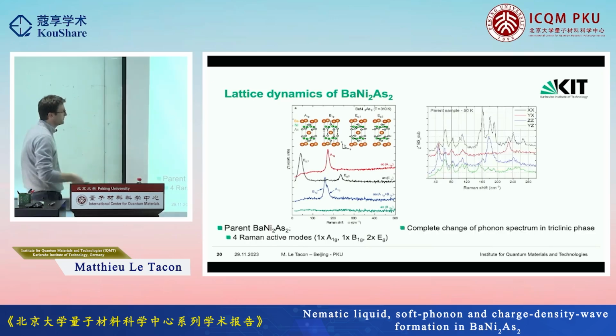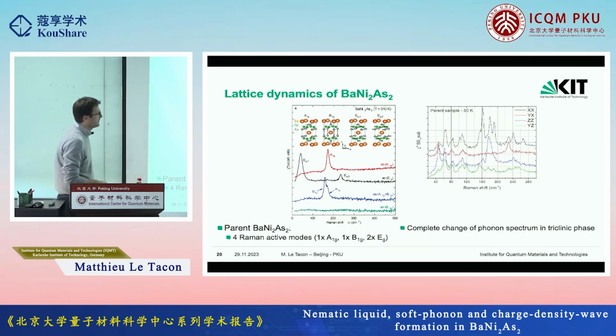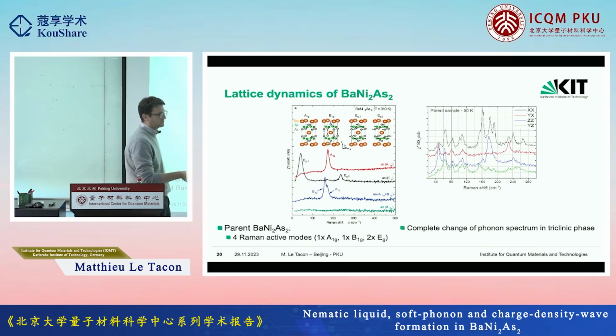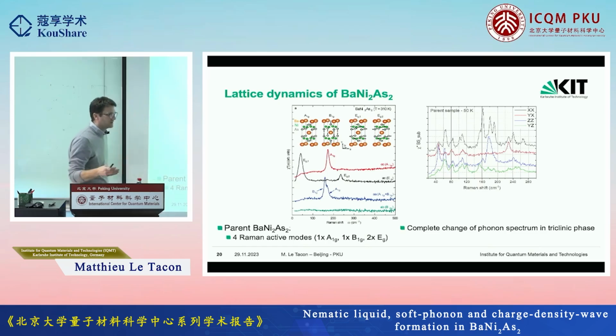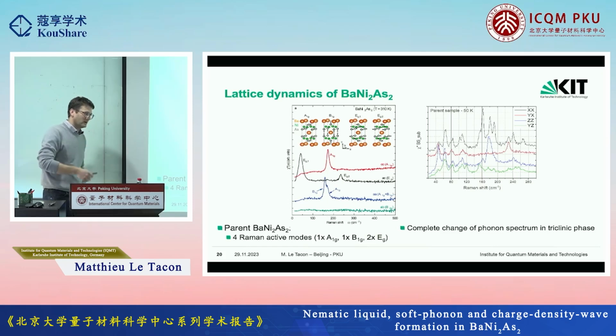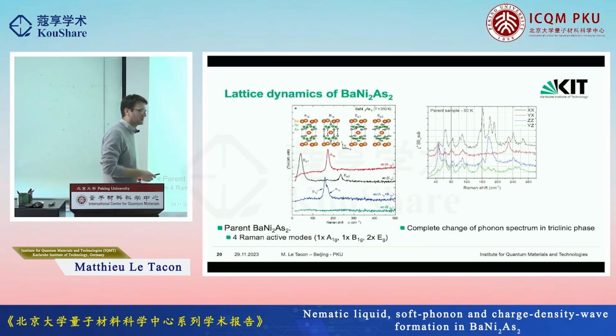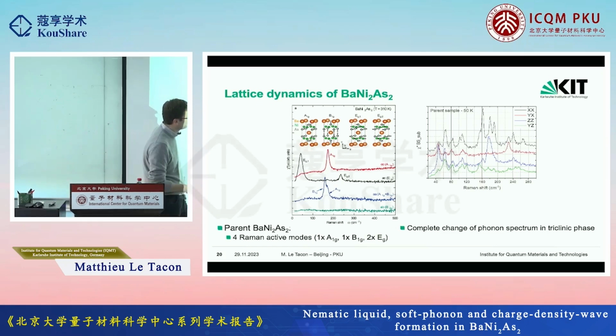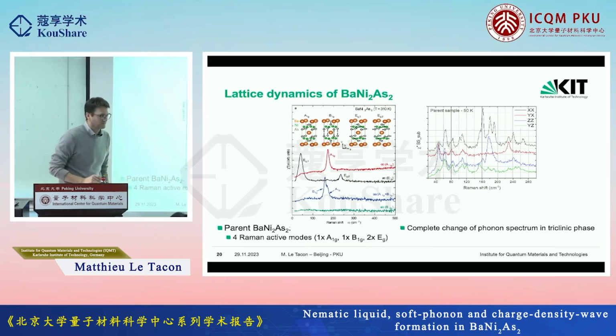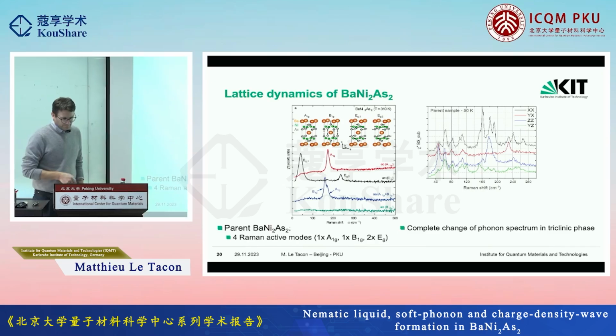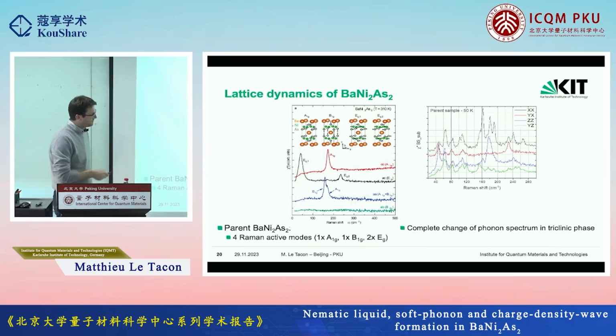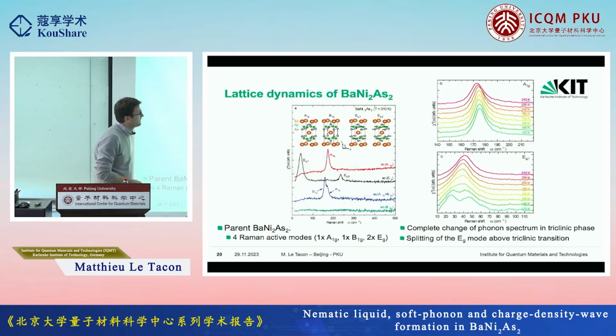So first, I go to 50K, and then at 50K in the parent compound, I am in the triclinic phase, with this awful 3x3 commensurate charge density wave and this triclinic transition. And so, yes, I can see immediately, without understanding anything about the spectrum, that I'm in the triclinic phase. There's no doubt about that.